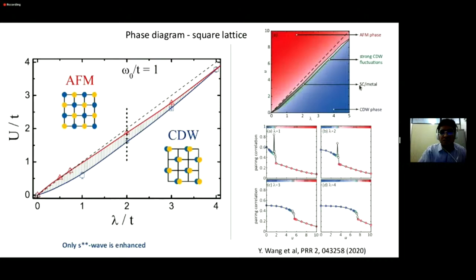But at some point, this result was in line with another very recent result, where people used the Lang-Firsov transformation to analyze the same model, and they see that the region at the middle, in between antiferromagnetic and CDW, presents D-wave superconductivity. So it differs from our results, but that's fine. Both of them are not so sure about the symmetry, but we are sure that here we have superconductivity at the middle. So the competition between CDW and antiferromagnetism can lead to superconductivity, in fact a superconductivity that is not on-site s-wave.